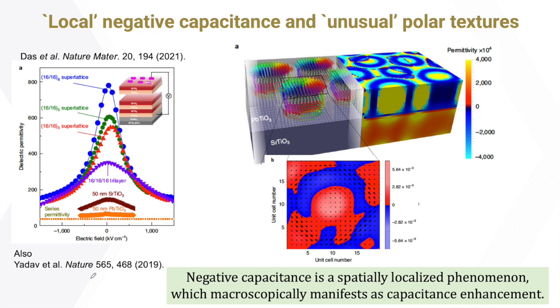A couple of slides back, I showed a macroscopic picture of how the stabilization of negative capacitance happens in a ferroelectric paraelectric heterostructure. Microscopically, the picture is much more complicated. Two related papers in this regard are these ones that came out over the last 2 years. In a ferroelectric paraelectric heterostructure, the polarization can form very interesting nanoscale polar textures, and within these textures, the static negative dielectric permittivity can occur in nanoscale regions.